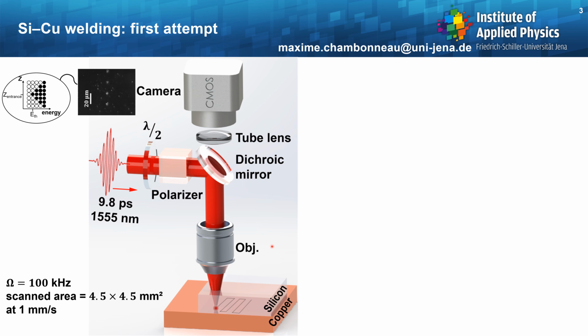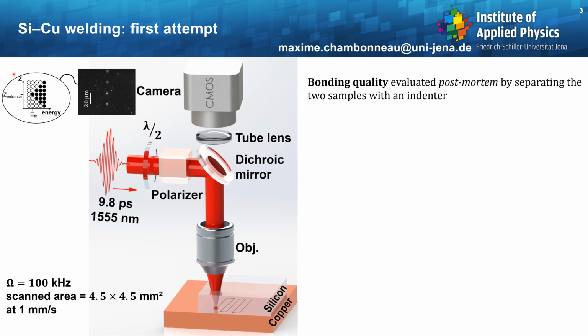Besides, we also have a microscope working in reflection and in dark field, relying on the same objective lens, a tube lens, and a CMOS camera. Thanks to this microscope, we can image the entrance surface of the silicon sample, and by doing a damage scan on this surface, one can position the geometrical focus with respect to the samples. We also evaluate the bonding quality by post-mortem separation of the two samples by means of an indenter connected to a force gauge. So let's have a first try.